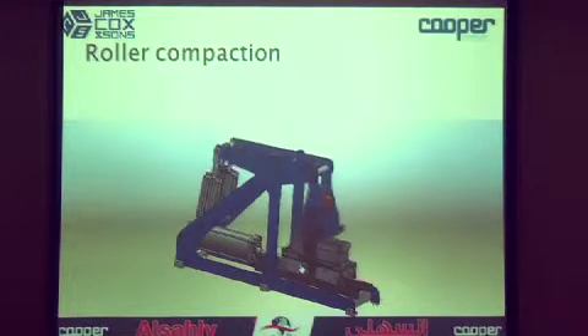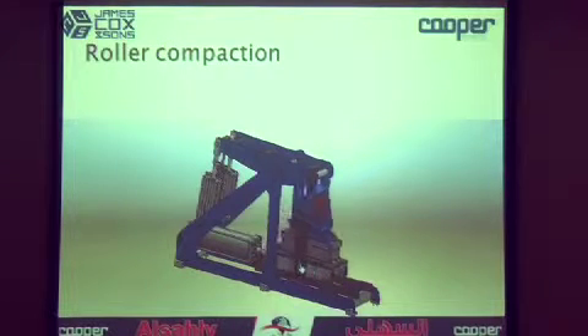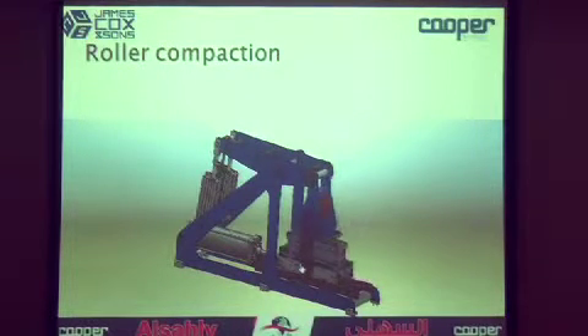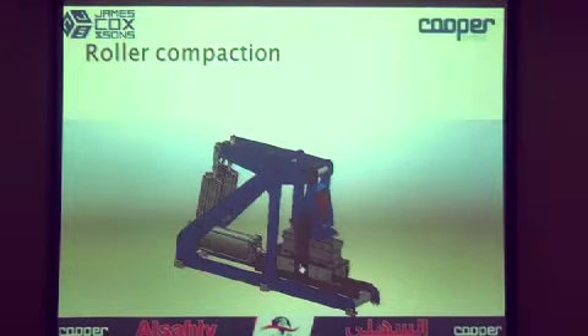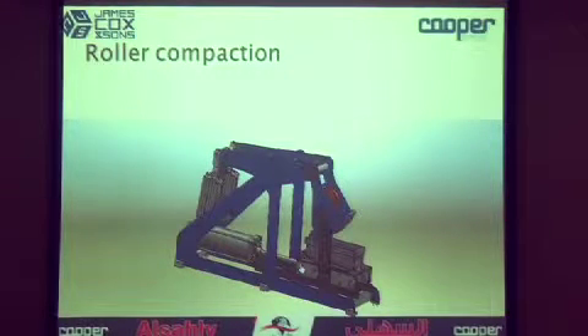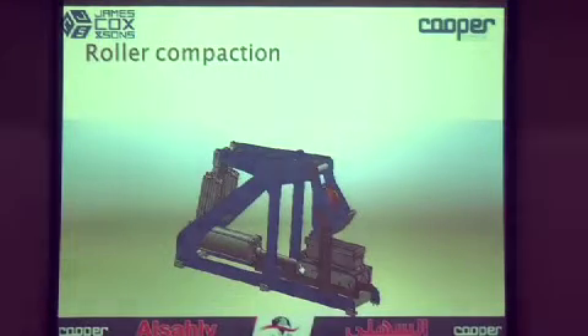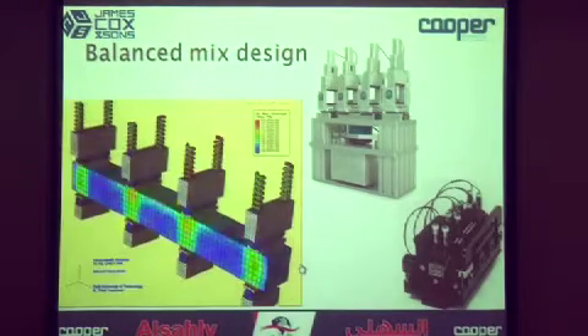So we put our mould in, our roller comes down, compacts until we reach our specified void content, our specified density. Then we take this out again and we can put it directly into our Hamburg wheel tracker, or our dry wheel tracker. Very, very popular method of making specimens for wheel trackers.